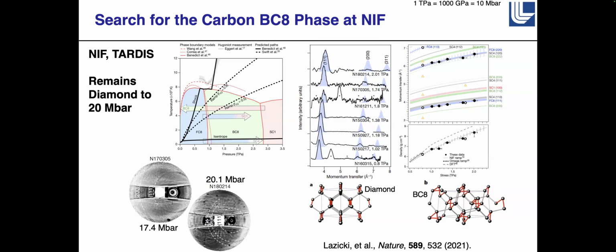And so our hope is that he's been mapping out the phase diagram, showing that you need high temperatures to form the diamond. So we're going to triple shock that experiment also. We're going to try to get to two shocks where we don't form diamond, and then in the final shock, start with an amorphous carbon material that will be at high enough pressure that we don't form diamond, we form the BC8.